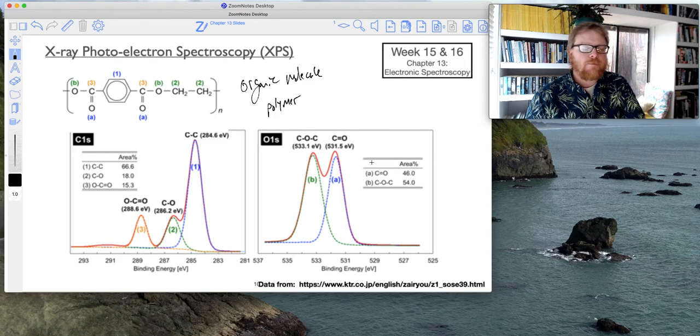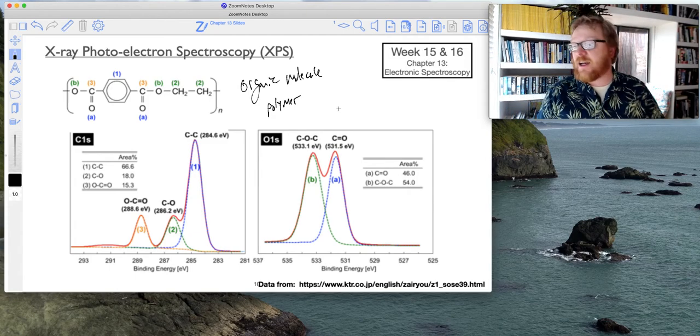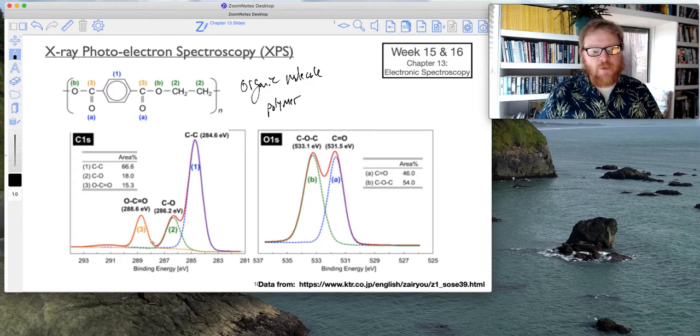Okay. And so you can see it's got various types of oxygens as well as various types of carbons. And so now, again, if we look at this 285 region where carbon always appears, you can now see it's quite dynamic. For example, the carbon-carbon bond shows up around 284.6 eV. And right here you can see that's corresponding to the carbon-carbon bond in this ring.